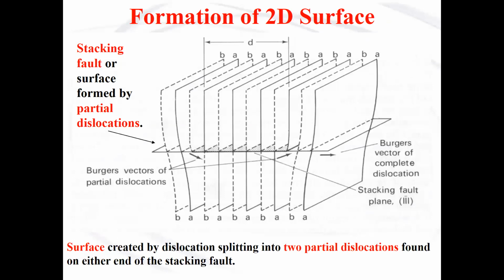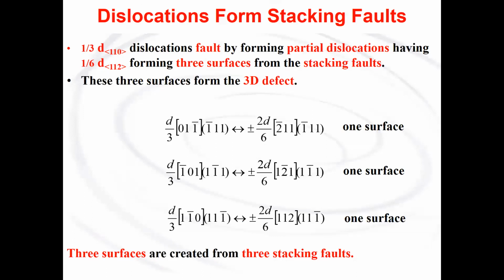And these dislocations can further split and form partial dislocations, and when they do, they form stacking faults. Here we have a stacking fault, which is a surface, and we can see a partial dislocation here and a partial dislocation here at either end of the stacking fault. And this creates a surface. So each one of these 3 dislocations can form partial dislocations.